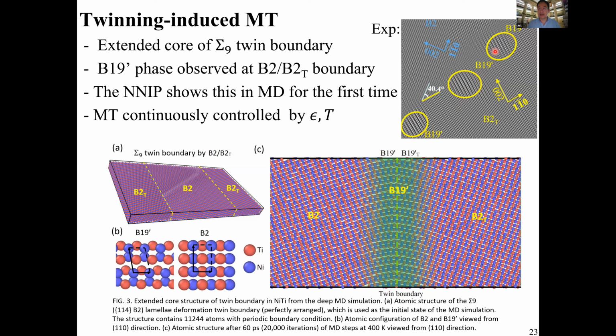So this is a TEM experiment where people find B19 prime-like domains on the twin boundary of B2 in the B2 phase. So even though B2 is the globally stable phase at a particular temperature, because of these near boundary motifs, these are highly glissile and give you very low hysteresis, pseudoelasticity, and shape memory effect, because you actually have pre-existing nuclei that are always living on these boundaries, ready